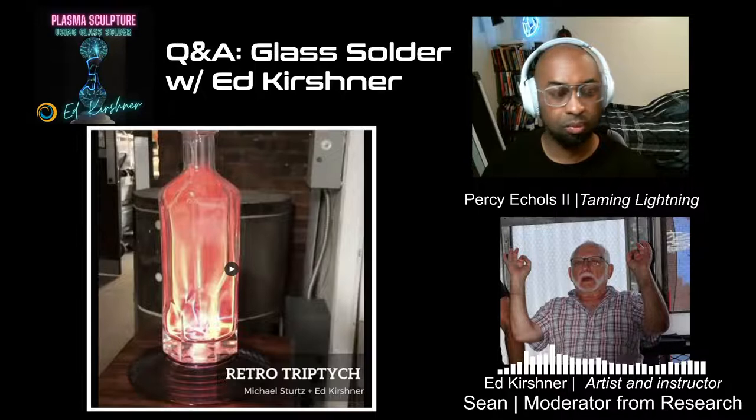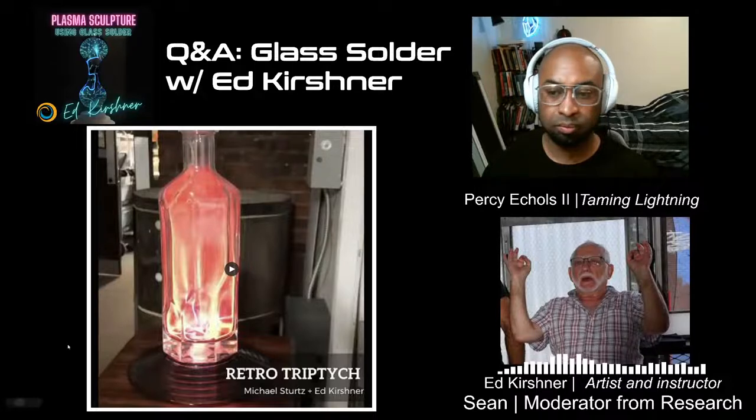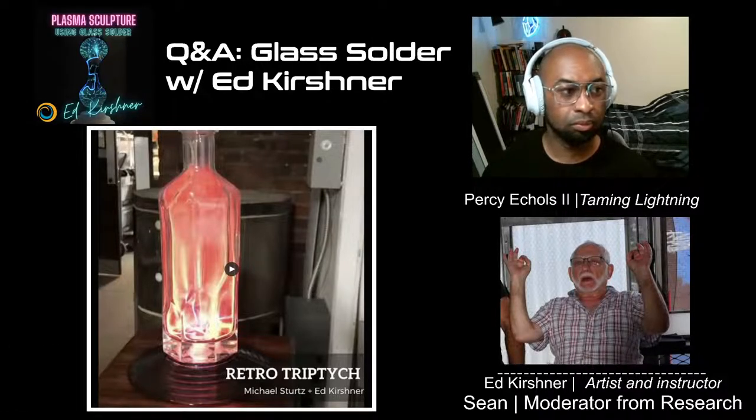The firing range I use basically looks very much like an annealing range, with the top being somewhat below the annealing temperature, but it follows the same pattern. When you're coming down, you come down very slowly from the top, and then you can drop a little bit faster.